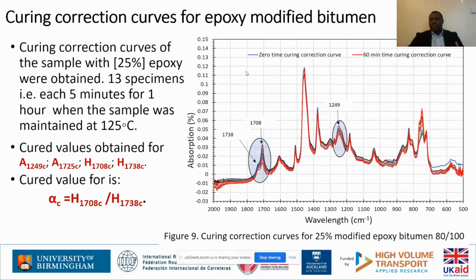We take that target sample, prepare it the same way as the other samples, then pick a specimen and collect spectra for those specimens every five minutes. It takes about one hour after mixing. The sample is kept in the oven for about 10 minutes, then removed. We take the first specimen and test it — called the specimen at time zero. Then every five minutes we keep sampling, determining the areas and heights of peaks for the spectral functional groups.